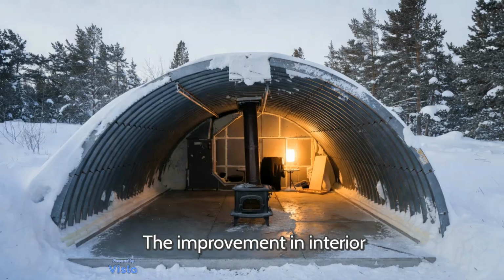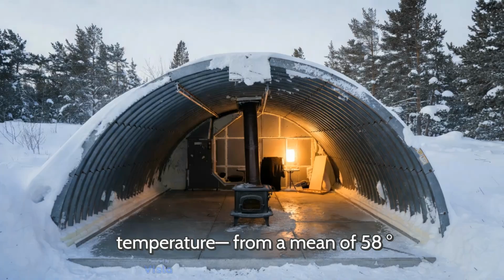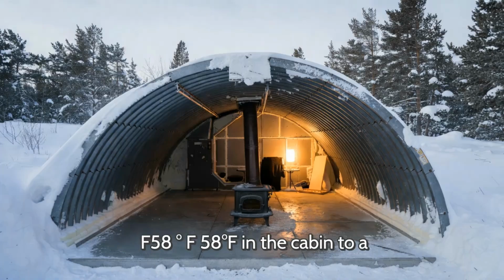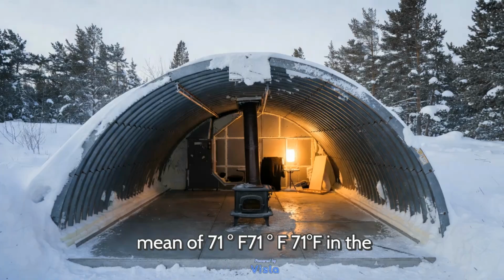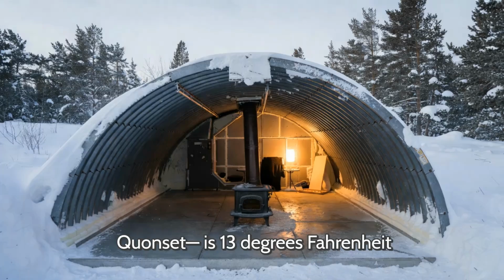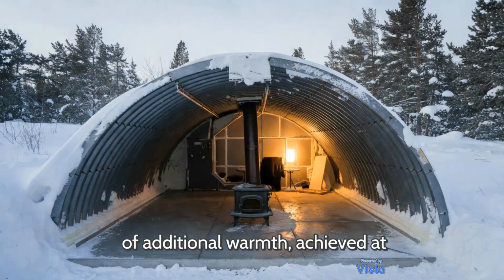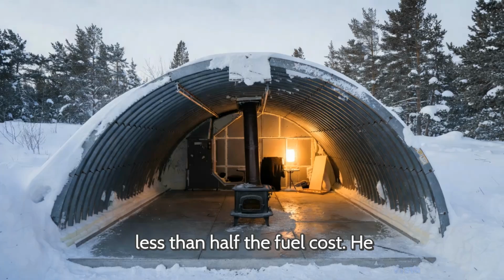The improvement in interior temperature from a mean of 58 degrees Fahrenheit in the cabin to a mean of 71 degrees Fahrenheit in the Quonset is 13 degrees Fahrenheit of additional warmth, achieved at less than half the fuel cost. He keeps a logbook.